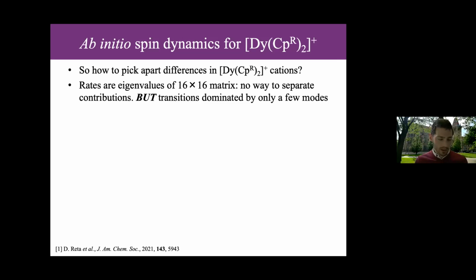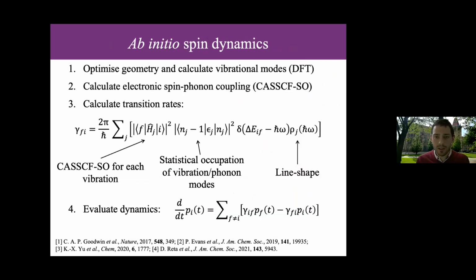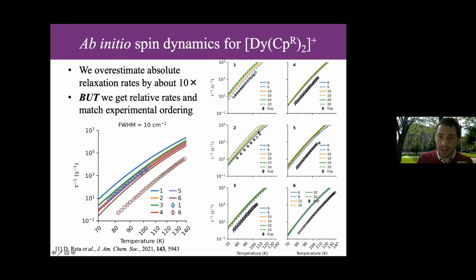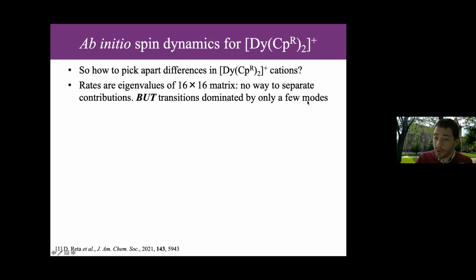So the key point to think about here is that because we have this delta function, if I go back to the expression, this delta function tells us that only vibrational modes that are very close in energy to electronic states will cause a relaxation step. And so that means that we must have only very few vibrational modes that contribute to any single transition.